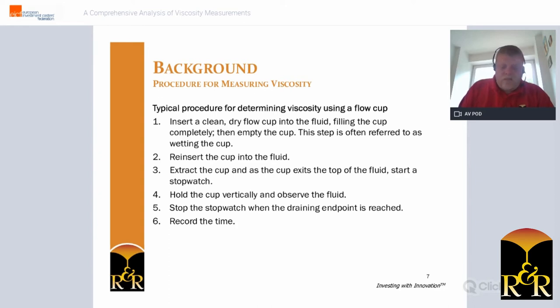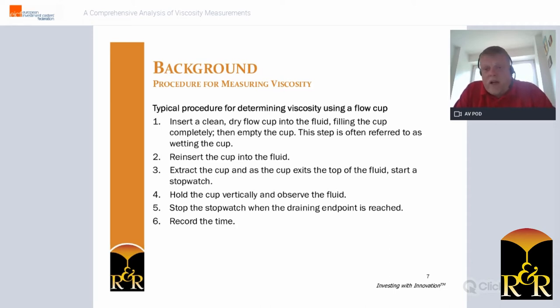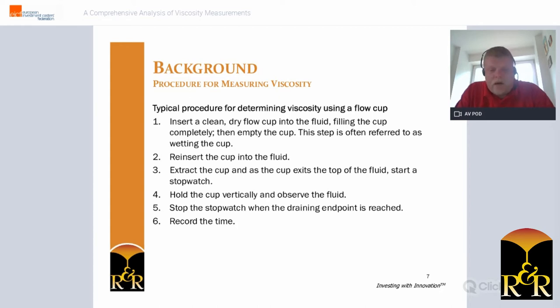How is viscosity measured in the foundry? Technically, these are not true viscosity measurements — they measure the efflux time of a slurry through the hole in the bottom of a cup. To measure this, we start by inserting a clean, dry flow cup into the slurry to completely fill it. It is then emptied so that the cup is fully wetted. This is very important because we want to ensure we are testing the slurry against itself, not slurry against the cup.